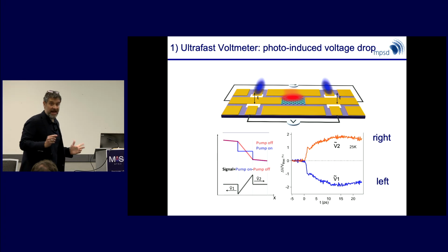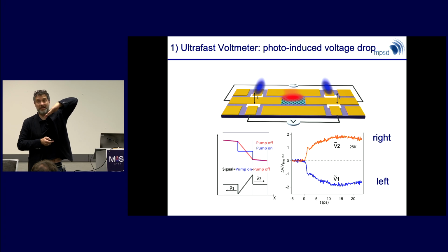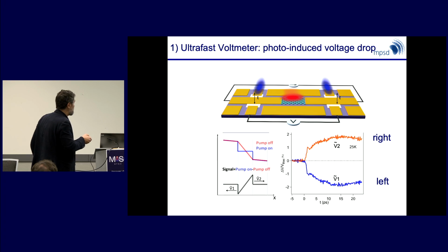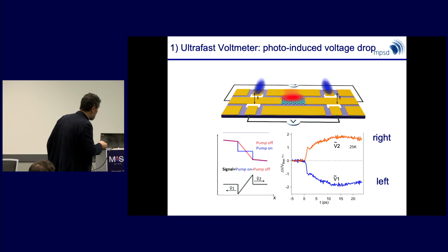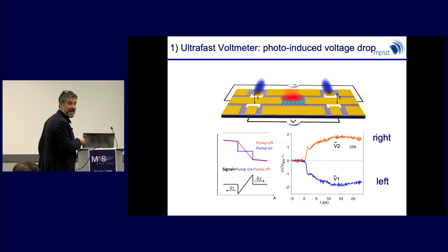Now you can start playing with this. The first thing you want to see is that if you take a metal and you photoexcite it, you're supposed to make the conductivity better. So you should go from a voltage drop of a metal to a voltage drop of a superconductor or a better metal. At these two Auston switches, this is my little schematic of what to expect. You start metallic above Tc. You photoexcite it at 7 microns. This was the voltage drop on the C60. Imagine that I'm making it superconducting.